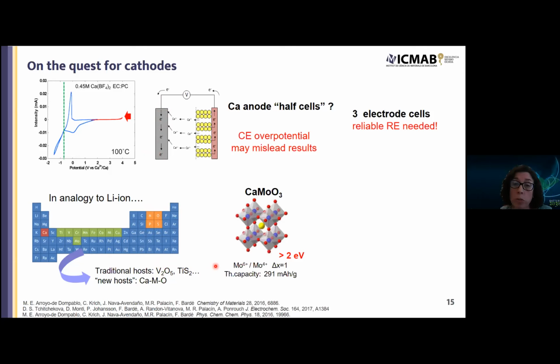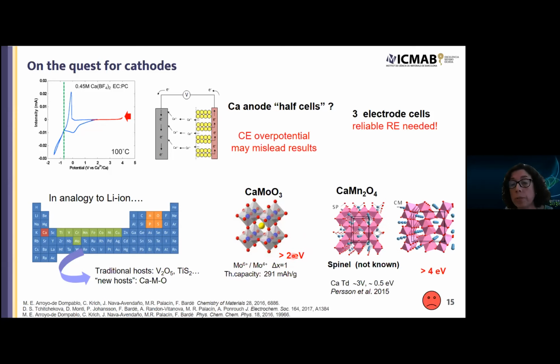So one of the compounds which we thought was interesting was perovskites, because this is a very rich family of calcium metal oxides, and amongst them molybdenum compounds seem to be very interesting, and we were able to prepare it, but there was no way to electrochemically extract calcium from the crystal structure, which we understood with the help from Elena Arroyo at Universidad Complutense de Madrid, who did the DFT calculations and was able to realize that the migration barrier for calcium in this crystal structure is huge, is 2 electron volts.